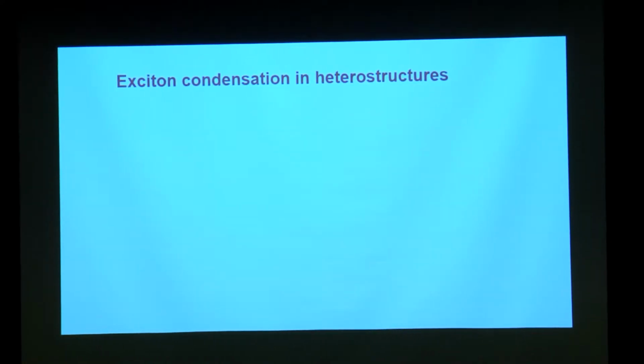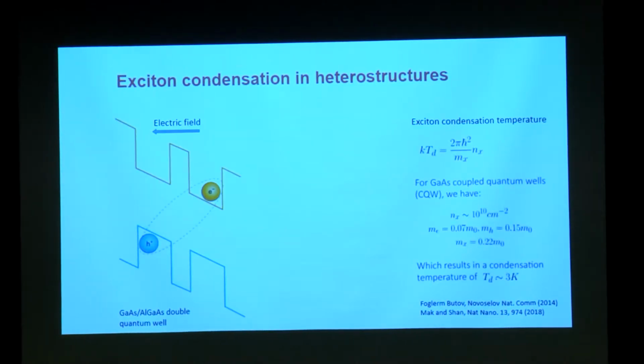Okay. But that's not the reason they are interesting today. That's not the only reason. So let's look at what kind of structures one can create, once you shine light on a semiconductor material and create an exciton, to look at exciton condensation. This work has been going on for quite a while, particularly in the case of gallium arsenide, aluminum gallium arsenide quantum wells, where you apply an electric field and you create, this is a quantum well, this is another quantum well, these kinds of indirect excitons. The reason behind the indirect exciton is that the electron and hole cannot fall on top of each other and vanish, but they form a long-lived bound state, and this has been one of the major reasons for creating this biased double quantum well to look at the excitonic condensation process.